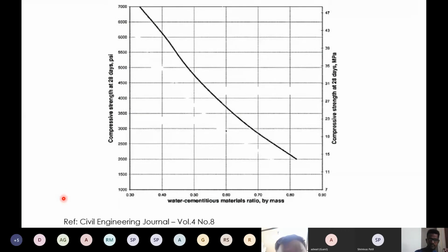So this is the graph that I took from the Civil Engineering Journal, volume 4, number 8. The porosity of the concrete directly affects the strength of the concrete. The more the porosity, the lesser the strength, and the porosity depends on the water cement ratio. Here, as you can see in the graph, on the x-axis is the water cement ratio from 0.3 to 0.9, and on the y-axis is the compressive strength in MPa of 28 days compressive strength. On the left-hand side of the y-axis is the compressive strength in PSI.